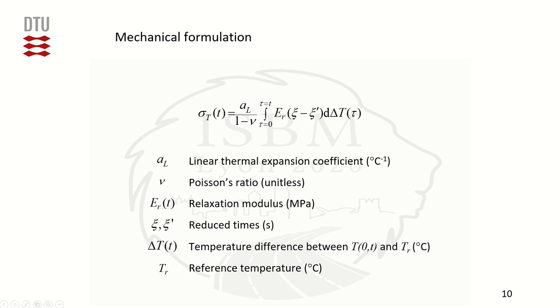Initially, the half space is considered completely stress-free at a reference temperature of 0 degrees Celsius. If the material is exposed to a constant temperature level above this reference, it can approach a stress-free state provided sufficient relaxation time is allowed. Conversely, if the material is exposed to a constant temperature level below this reference, induced stresses do not approach zero regardless of the amount of relaxation time allowed.